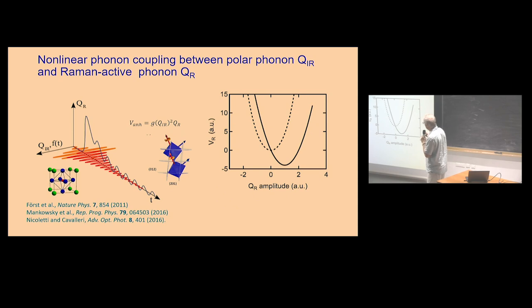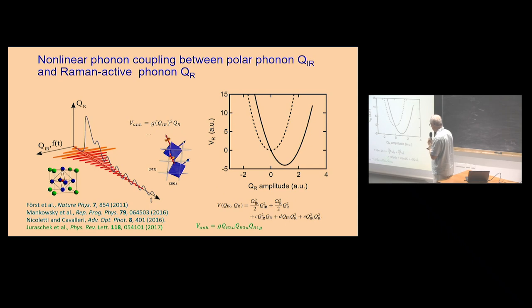So what happens here, practically, you change the potential, which is harmonic without pumping. And due to this quadratic coupling, you get another potential with another minimum, and you can change the crystal structure. And such coupling is not only this quadratic coupling, but you can also have quadratic coupling of an infrared or Raman mode with an infrared mode, or biquadratic coupling. And later it was even generalized by Dominik Juraschek, that you can have trilinear coupling of 2 infrared modes with 1 Raman mode. You can change the interatomic potential using this pumping.